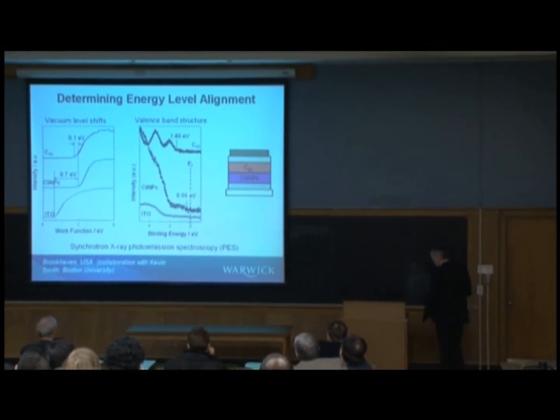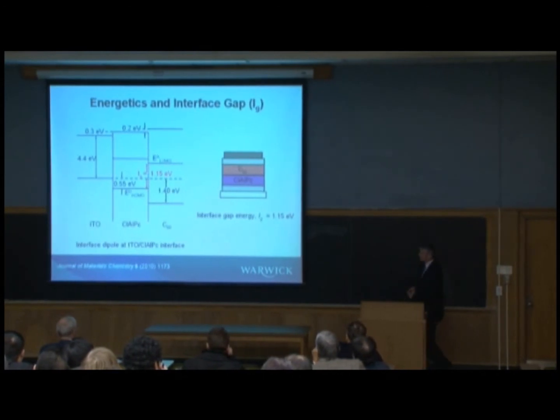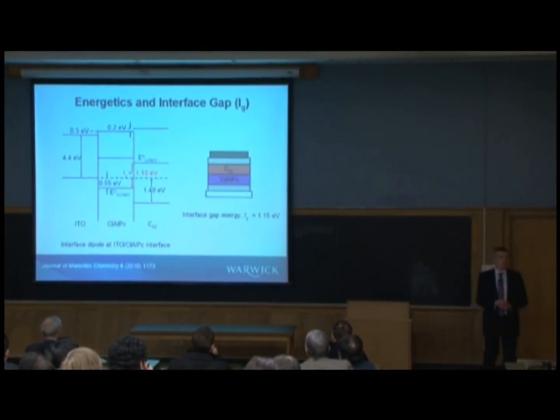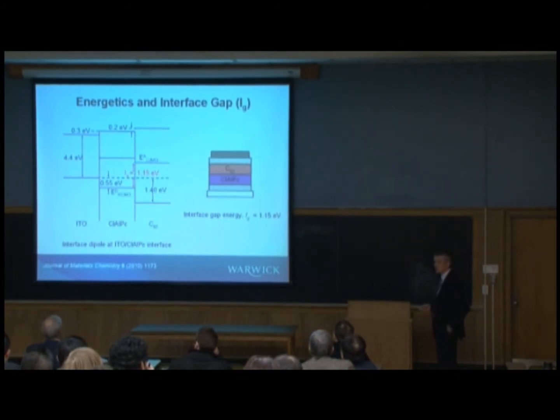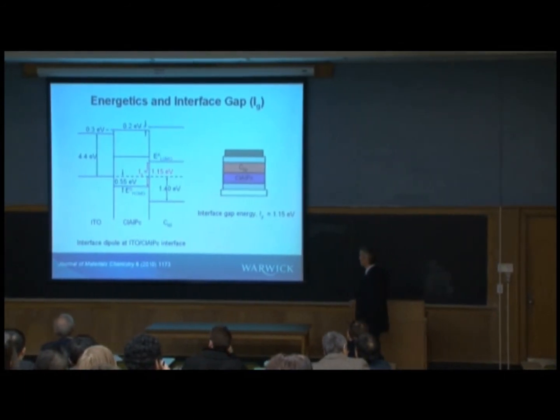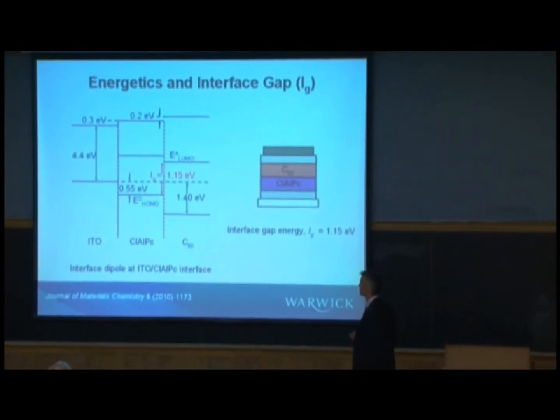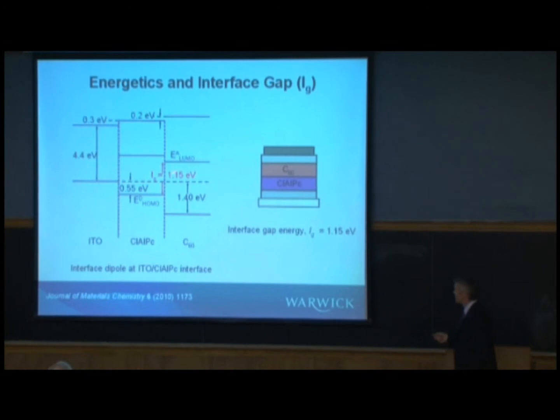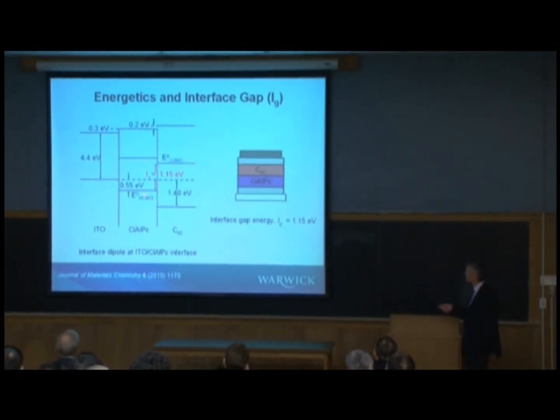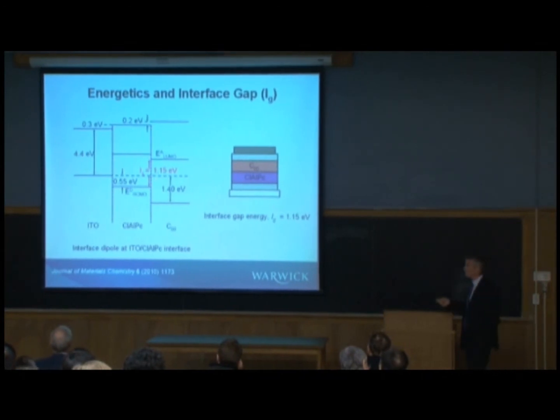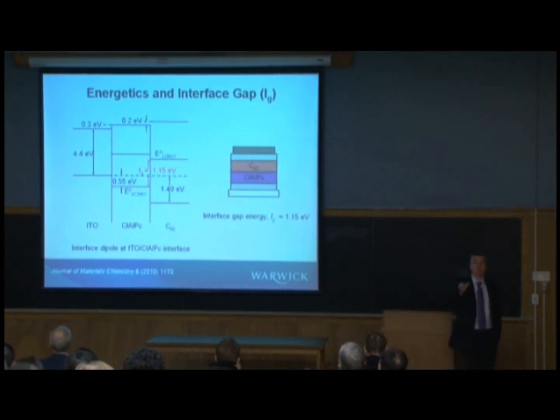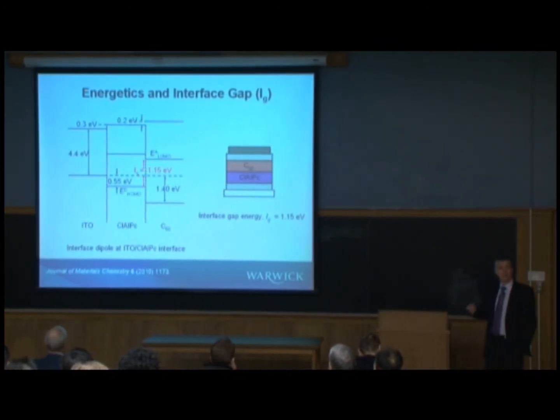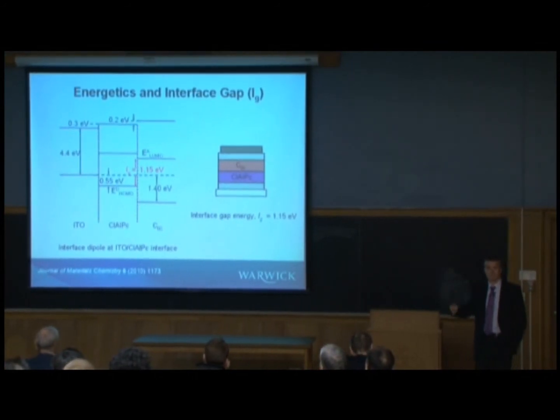Out of that, you can draw energy level diagrams. This is a methodology that's well known in the inorganic semiconductor world, but really hadn't been done much in the organic world. As I said, people are now doing this with some rigor, which is great. So this is the energetics for that particular combination of materials. The point I want to concentrate on is that the interface gap energy, which is this energy here in red, the difference between the HOMO of the phthalocyanine and the LUMO of the fullerene, is 1.15 electron volts based on that data for this material system. So clearly the open circuit voltage will be somewhat less than that because you've got some losses associated with dissociating the exciton.